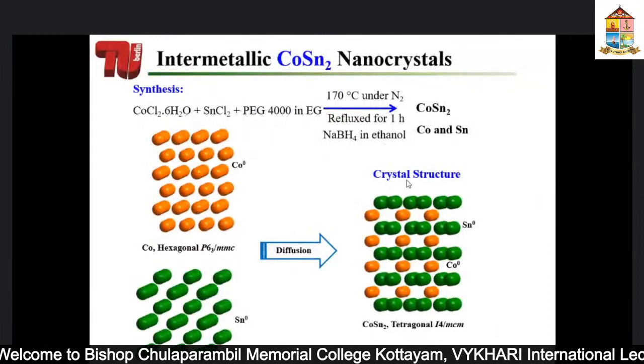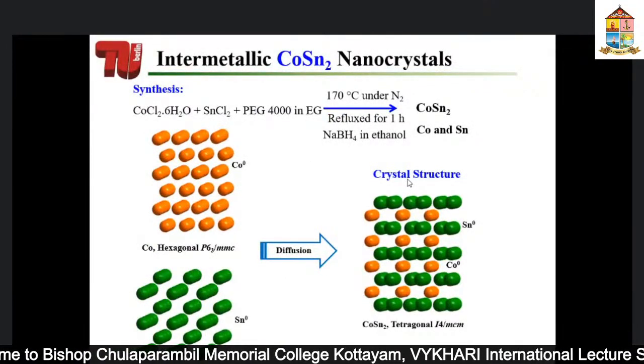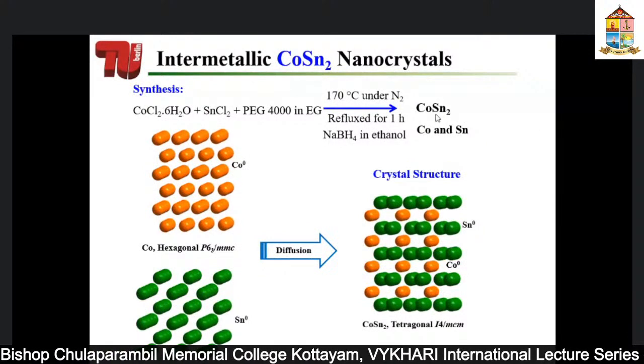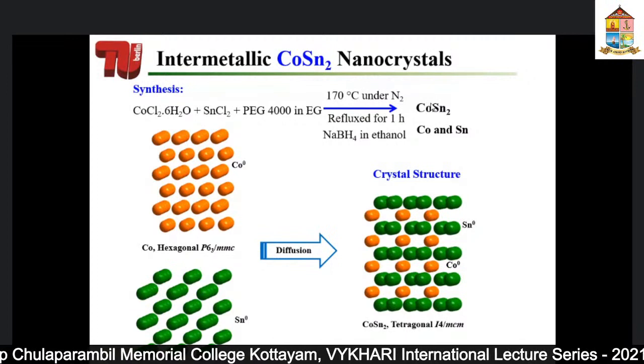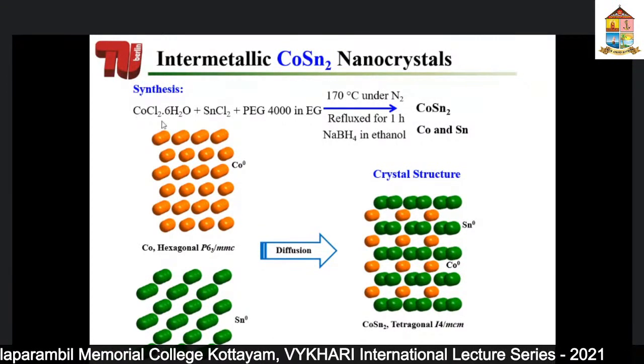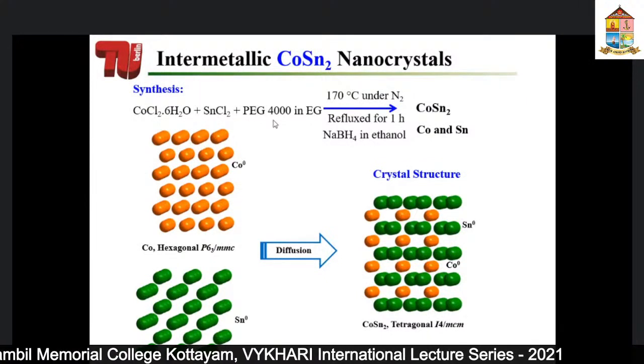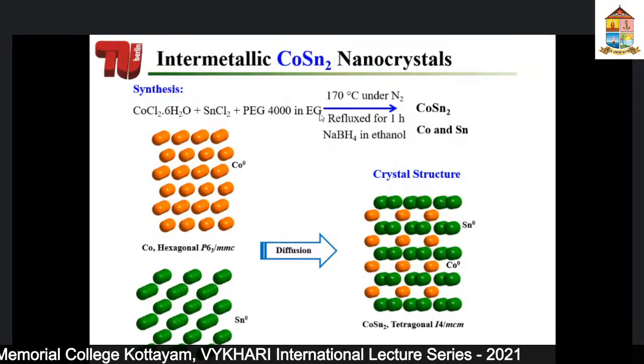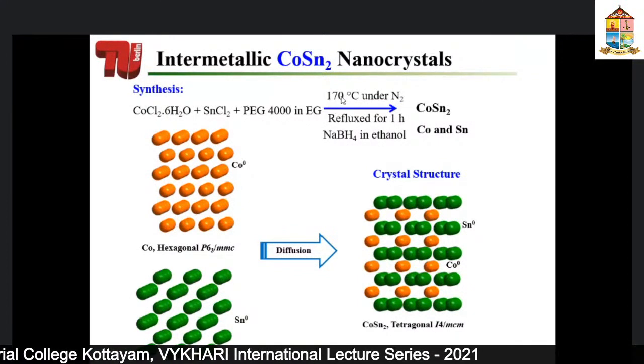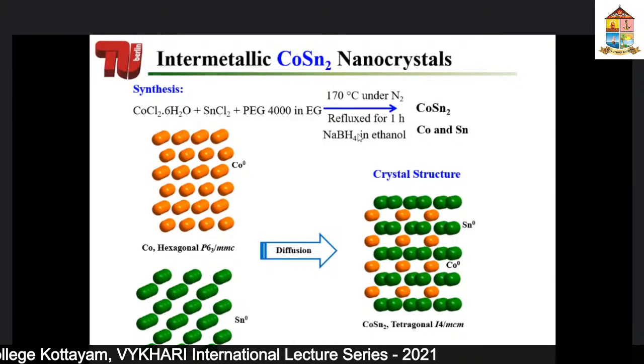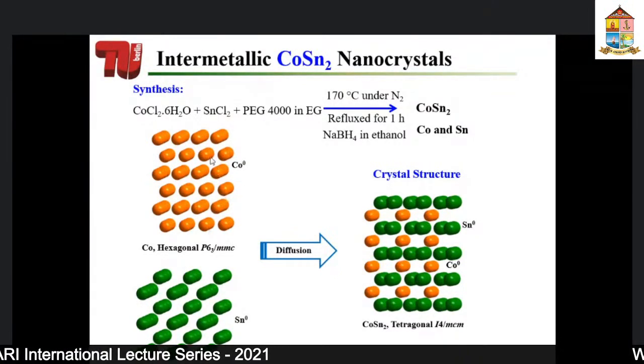Okay, we did this in a very simple way. We wanted to prepare a cobalt stannide because it is known in the literature that it's a very conductive material. And we took a very simple solution of cobalt chloride and tin chloride. We added polyethylene glycol as a capping agent in ethylene glycol, which has quite a high boiling point, almost 170 degrees. We refluxed and we added sodium borohydride to reduce these metals. So there is a reduction of the metals. So what happens? First cobalt is reduced to cobalt 0 and tin is reduced to tin 0. And they slowly diffuse through each other through a Kirkendall effect, and then you form something like CoSn2, which is tetragonal in structure.